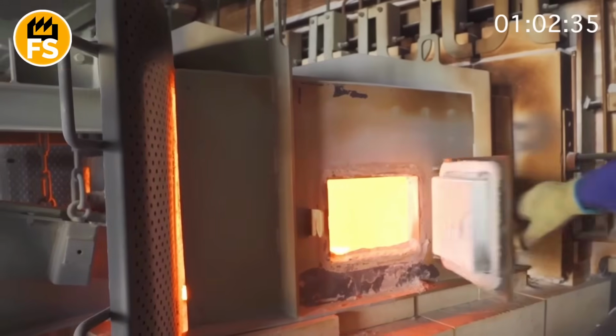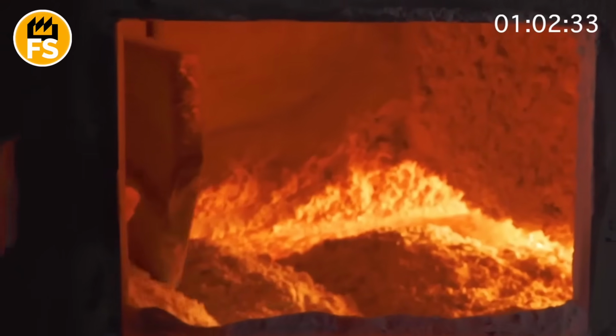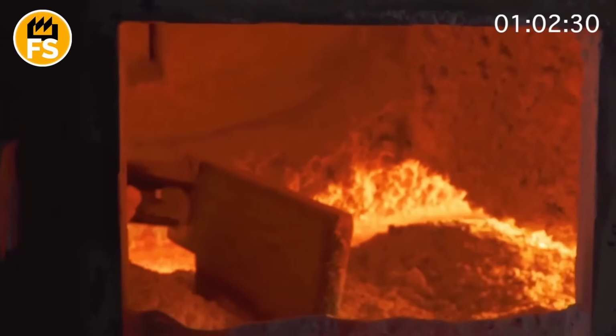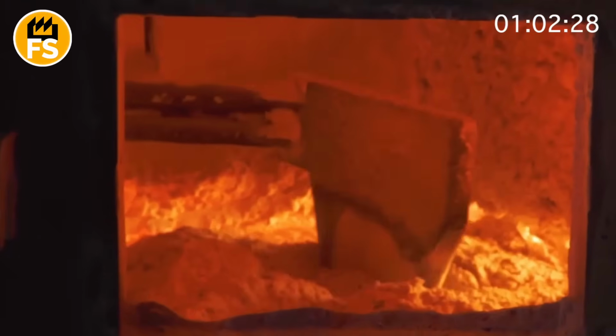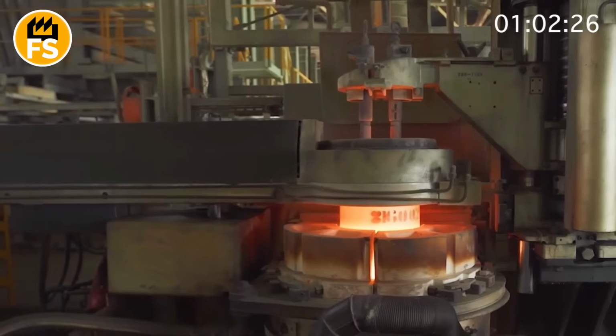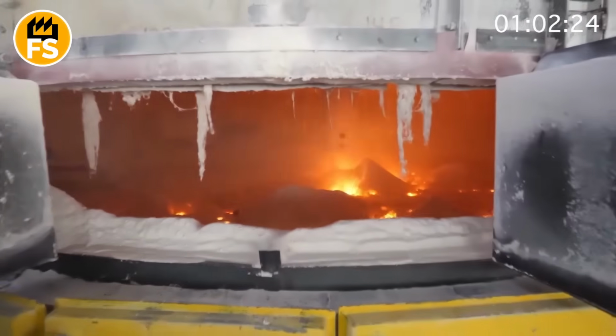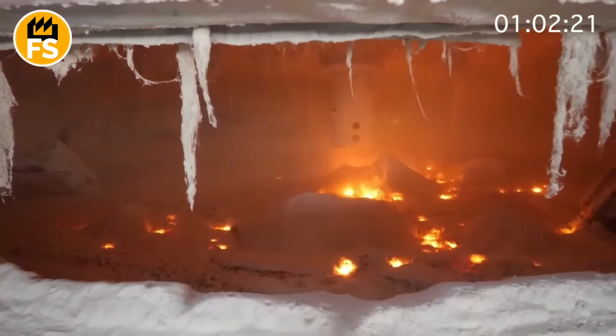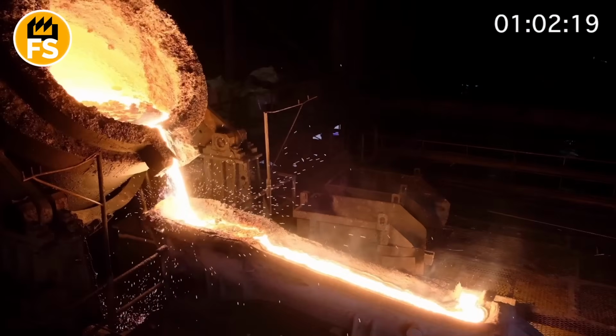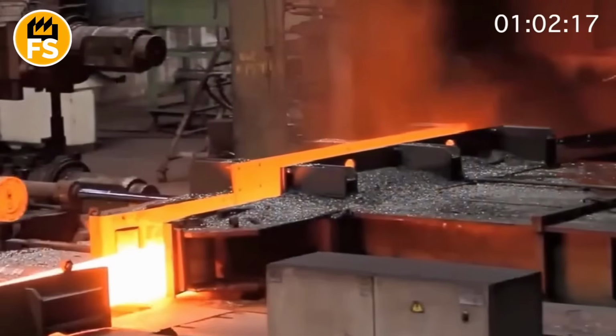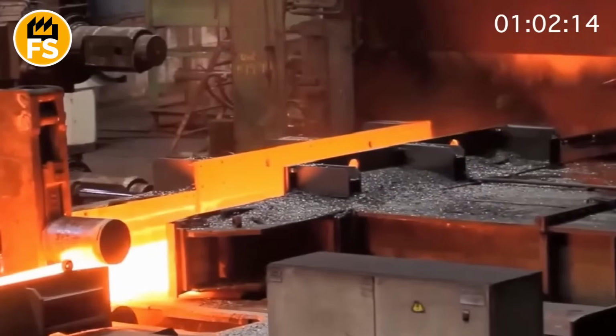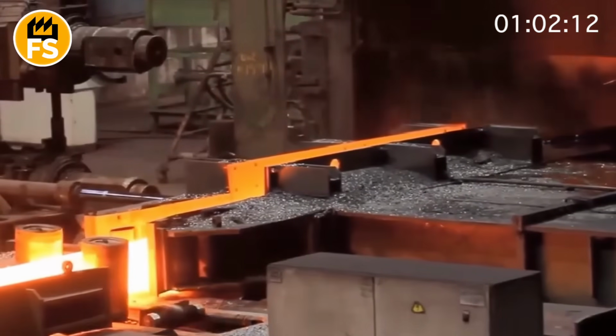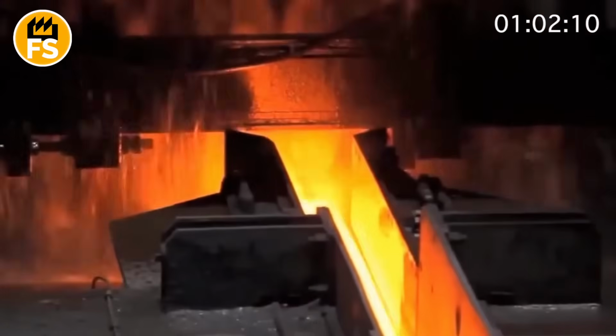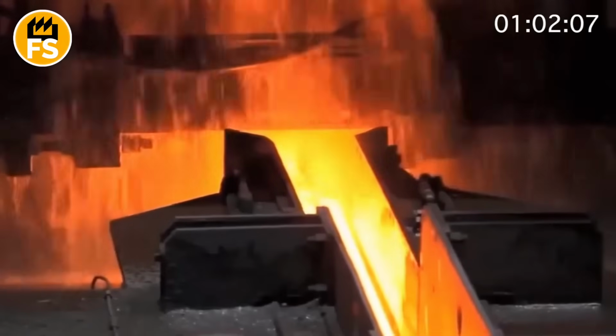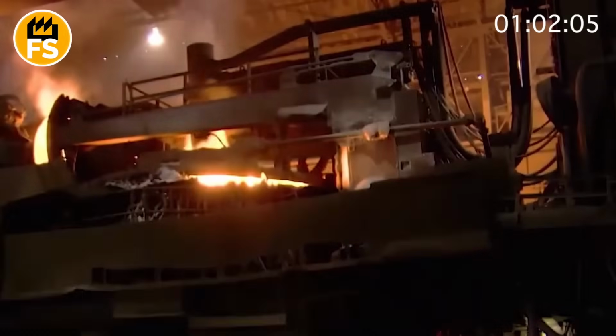Large, sealed like a vacuum capsule, it slowly swallows the blanks. Inside, an oxygen-free atmosphere, often with nitrogen or argon, to avoid oxidation. The temperature rises gradually to avoid creating stress in the metal. At its maximum, about 1,112 degrees Fahrenheit for aluminum, the filler metal begins to flow, but not boil. It fills the gaps, like liquid gold, penetrates the smallest crevices between the tubes and fins, binding everything together, like lava squeezing mountain rocks into a single block.